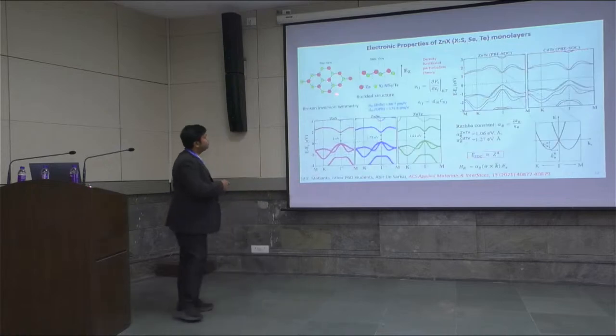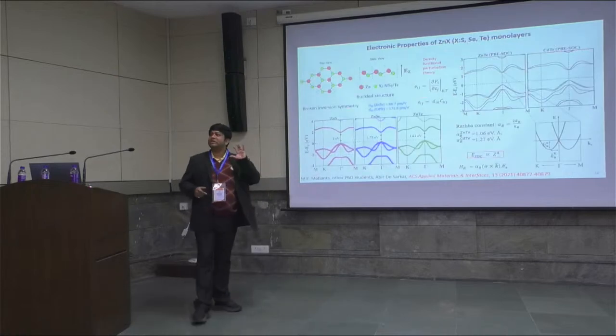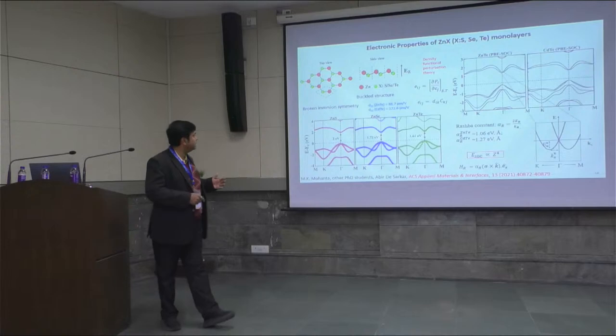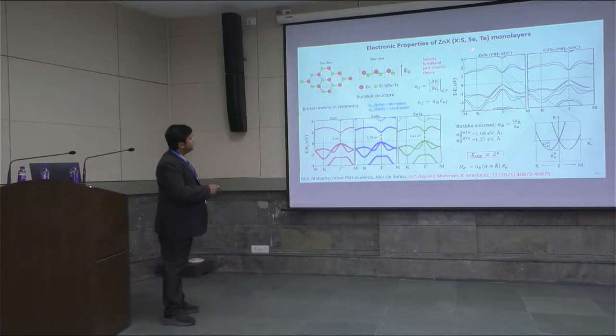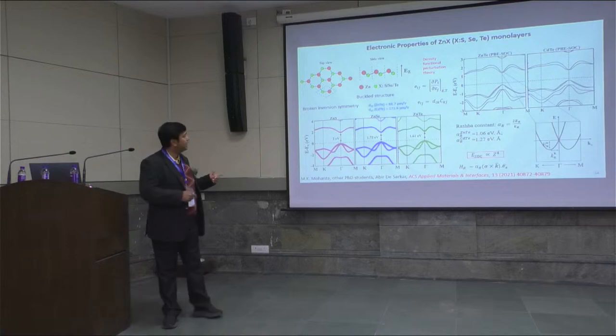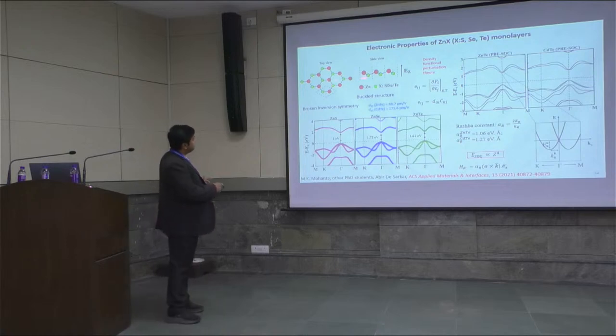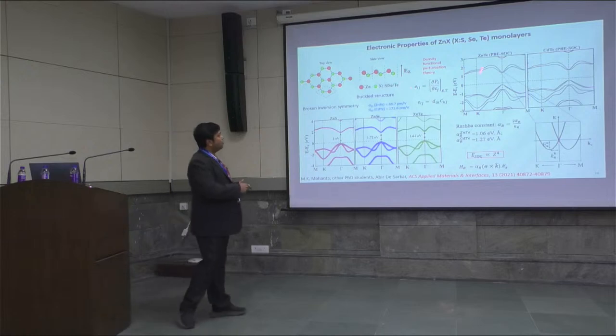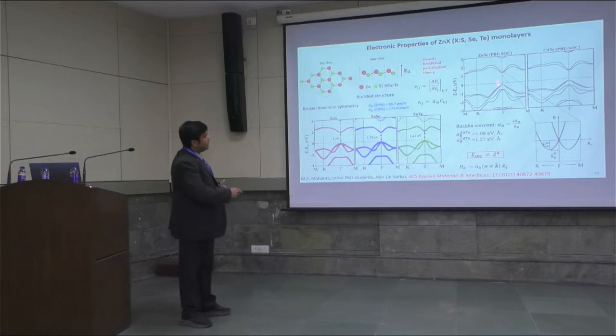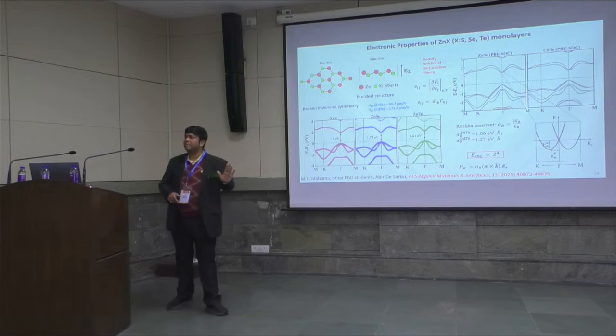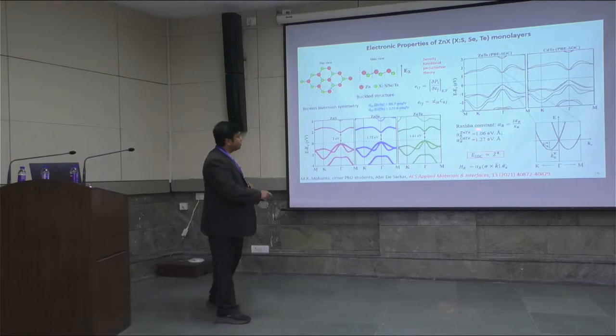So we have proposed a couple of monolayers which exhibit a combination of all these three properties, like ZnTe and CdTe monolayers. They have a polar buckled structure and a hexagonal honeycomb lattice as well. And because of this polar buckled structure, as I've been mentioning to you, an out-of-plane electric field intrinsically arises, which induces momentum-dependent spin splitting in the conduction band, as you can see. So one parabola splits into two parabolas. This is the momentum-dependent spin splitting, and this is the Rashba constant.